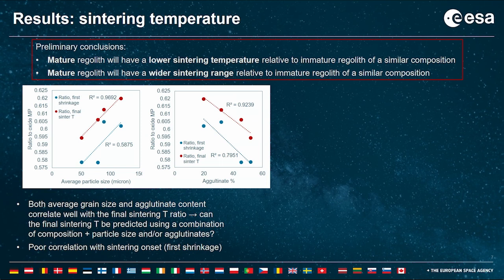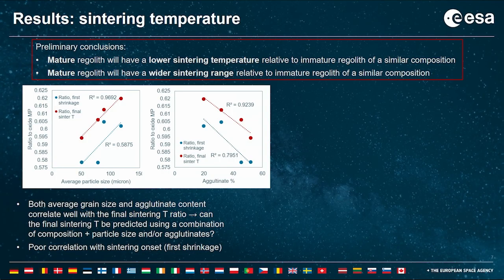And so here we might be able to say that we could predict the final sintering temperature based on a combination of these factors, so composition and particle size and/or agglutinates. It's not surprising that both of these things correlate because they correlate to each other, the average particle size and the agglutinate content, and so work is ongoing at the moment to use some specific tests with simulants to really tease out the difference between those things, so we don't have that to present just yet. But we do see a poor correlation with the sintering onset, so the beginning of that sintering stage.